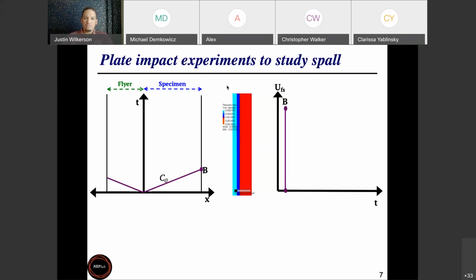Since everything is pretty one-dimensional, we typically visualize these things in terms of XT diagrams, because there's only one spatial dimension that matters, which is the X direction, or this longitudinal horizontal direction. And then the time scale is what matters quite a bit. On this XT diagram, the propagation of the shock front ends up looking like a line. The slope of this line is dictated by the wave speed of the material, which is a material property: basically the square root of the stiffness of the material divided by the density of the material. These shock waves are generated and propagate out after the impact occurs. One propagates into the flyer plate and one propagates into the stationary target material.